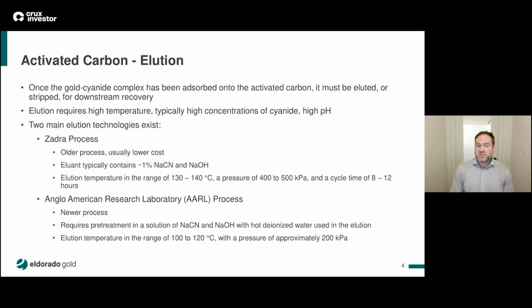The eluent is typically 1% sodium cyanide, and sodium hydroxide is used as well. Temperature in the range of 130 to 140 degrees, high pressure, and a cycle time typically of 8 to 12 hours. The main competing process is the AARL, or Anglo-American Research Laboratory process.